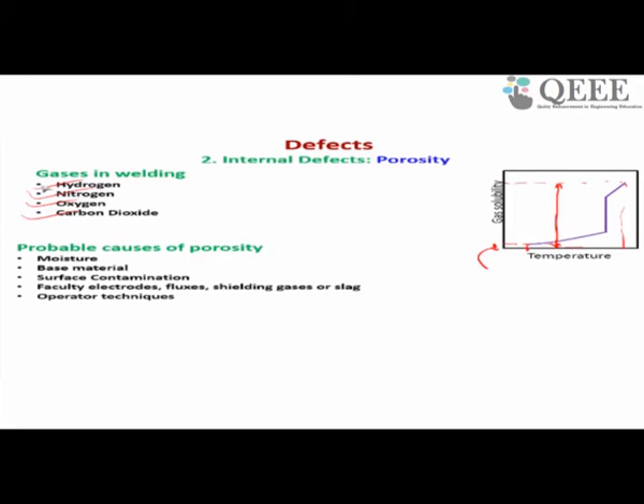What are the probable causes? We use electrode material, and remember we use it in shielded metal arc welding. We used a filler material, and the filler material was coated. The coated filler material has a high chance that it may absorb moisture from the atmosphere. Moisture is nothing but H2O. So from here hydrogen may come and oxygen may come.